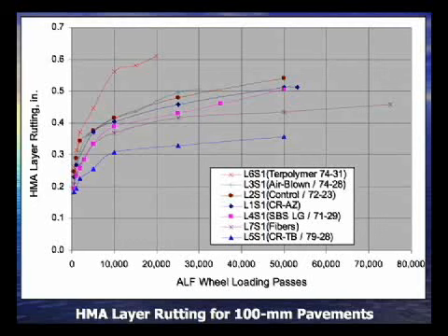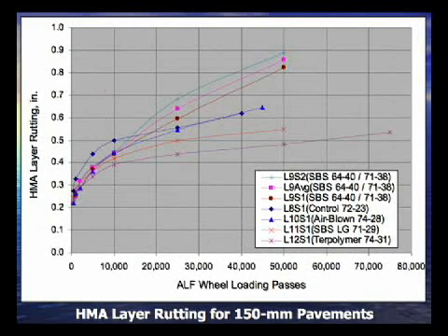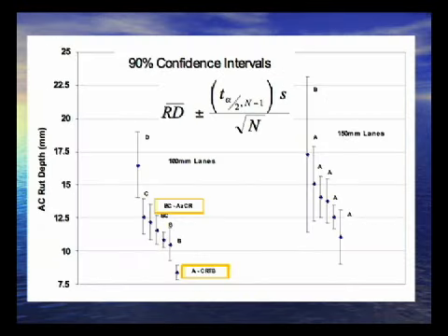So getting into the meat, this is what we see for the 4-inch sections. This is rutting observed only in the asphalt layer. This is rutting that is observed in the 6-inch layer. What I tend to look at rutting with is this type of graph. So this is 90% confidence intervals. We have 8 points along the wheel path, and actually we have some variability in field rutting. Even in well-controlled APT facility construction, you can have variability in rutting. And we see that here.